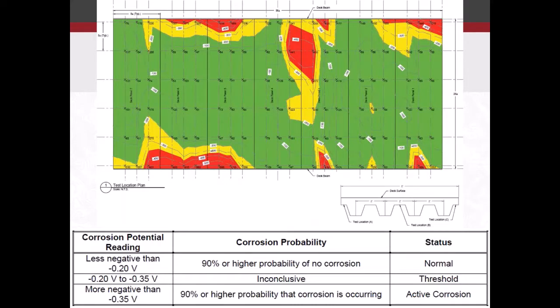We also plot this on equipotential contour lines. And down here at the bottom, we see this table. This is right out of the ASTM. Values that are less negative than 200 millivolts imply that there's a 90% or higher probability that there's no active corrosion going on. That's normal, not a whole lot of electron movement. Negative 0.2 to negative 0.35 is kind of inconclusive. That's kind of the threshold. Those are the yellow areas here. More negative than 0.35 volts, then there's a 90% or higher probability that active corrosion is occurring.